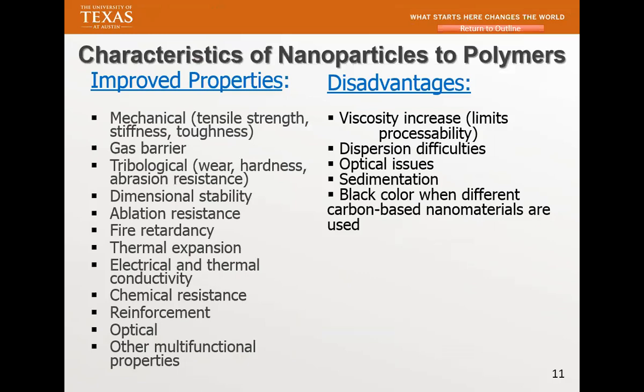The most important thing I want to caution you about is dispersion difficulty. Dispersion is very important because you put the nanoparticles in there, you don't disperse them correctly, you'll never see what they tell you about these properties. Another thing is optical issues. You deal with a transparent polymer, and you put carbon base in there, everything is all black. You put a little bit of carbon black in there, it's going to be all black, and for the application you need transparency, it's not going to work. It may give you other properties. So those are the things.